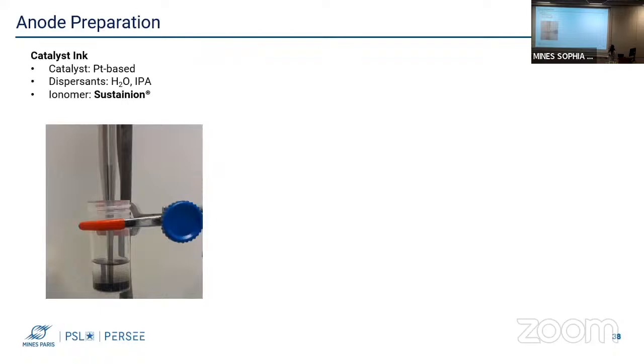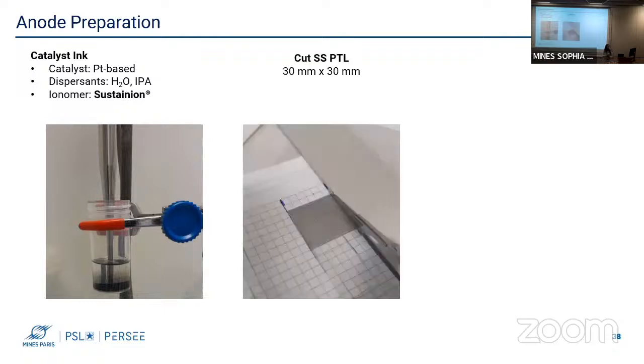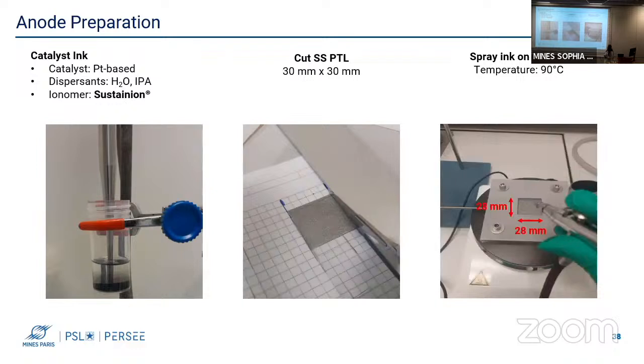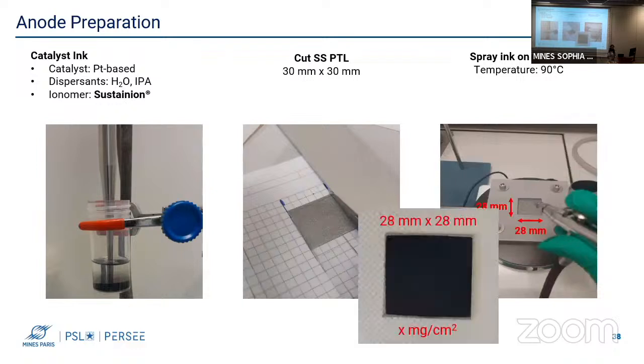This consists of obtaining a catalyst ink, which is a mixture of the desired catalyst to be used at the anode, the dispersing medium, which is a mixture of water and isopropanol, and the ionomer. In this case, it is chosen to be Sustainion in an attempt to improve the performance from the literature and for it to be compatible with the membrane. This ink is well sonicated and then sprayed on a stainless steel porous transport layer cut into the dimensions of the cell using a homemade spraying system in order to finally obtain the anode at the desired catalyst loading.